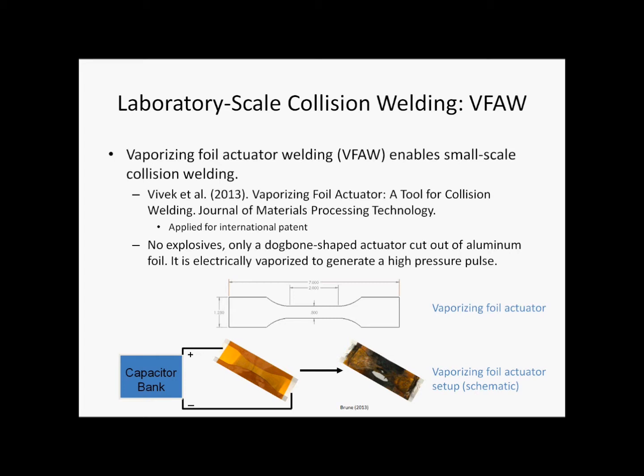When the capacitor bank is discharged, the foil is electrically vaporized within tens of microseconds, and the expanding gas from this rapid vaporization provides the driving force to propel a thin sheet of metal into a high-speed collision with a target plate. The peak velocity of the flyer plate is typically on the scale of hundreds of meters per second. Thus, this technique is able to achieve explosive-like speeds without using explosives.